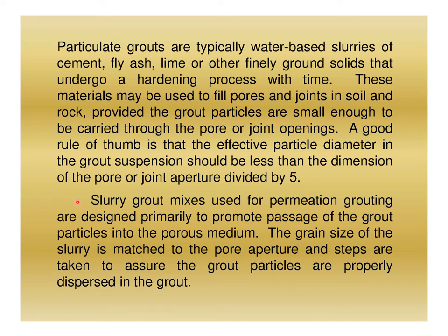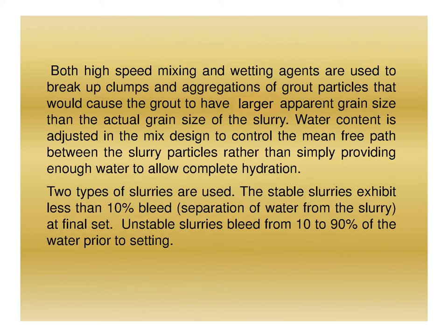Slurry grout mixes used for permeation grouting are designed primarily to promote passage of grout particles into the porous medium. The grain size of the slurry is matched to the pore aperture, and steps are taken to ensure grout particles are properly dispersed. Both high-speed mixing and wetting agents are used to break up clumps and aggregations of grout particles that would cause the grout to have a larger apparent grain size than its actual grain size.